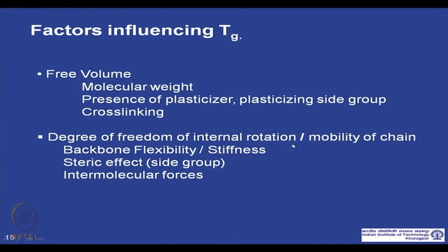So, the degrees of freedom for internal rotation, or the mobility of the chain, affect the value of Tg, and this depends upon the stiffness or flexibility of the backbone, steric effects, the side groups present, and intermolecular forces. The more intermolecular forces, the less is the freedom to move.